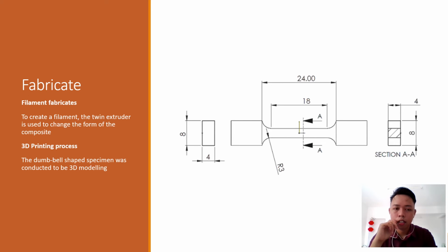After the wood dust is mixed with PP with a different ratio of MAPP, I will fabricate it into filament using a twin extruder, which can change the form into pellets. Then after I get the filament, I will print it out using 3D printing into the specimen shape, which is a dumbbell shape. The figure shows an example of the dumbbell shape that I'm going to fabricate.